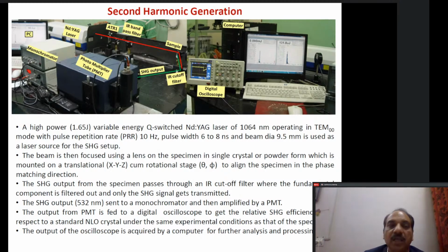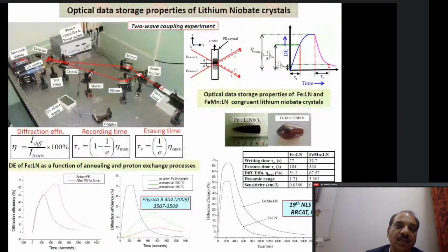So this is a complete setup which you are seeing, and this is the procedure which we use for measuring the second harmonic generation. And I told that lithium niobate is a very good optical data storage material, and the two-wave coupling experiment is what we do to find out its data storage properties.